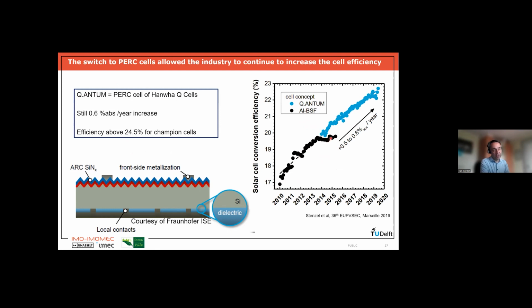The black dots I showed you before are the evolution of the aluminium BSF cells, which stabilize around 20%. And somewhere around 2014, the company then also started producing in their line the PERC cells. They call it here Quantum. That is just the name that they give to their PERC cell concept. And you see that with these PERC cells, they reached much higher efficiencies, above 23% at some point. And you see they could actually continue this increasing slope of around 0.5 to 0.6% absolute increase in their production efficiencies. And in the meantime, for these PERC cells, typically efficiencies around 24.5% have already been reached by several companies and so on. So it's way higher than what we can do with the aluminium BSF.